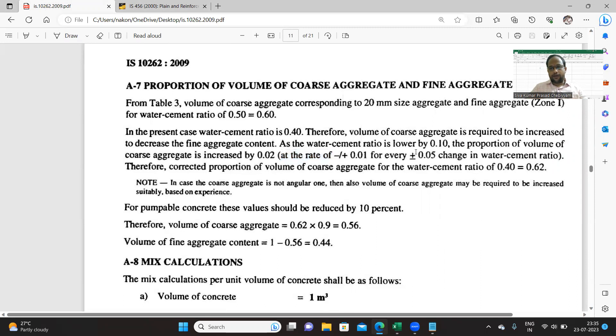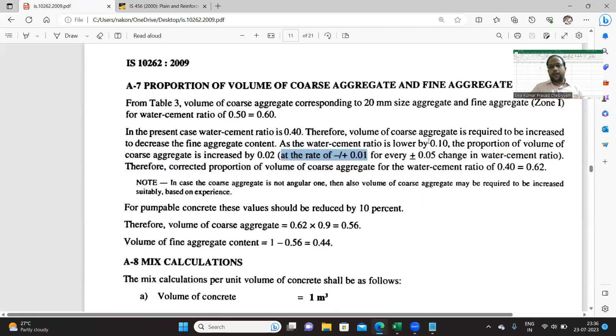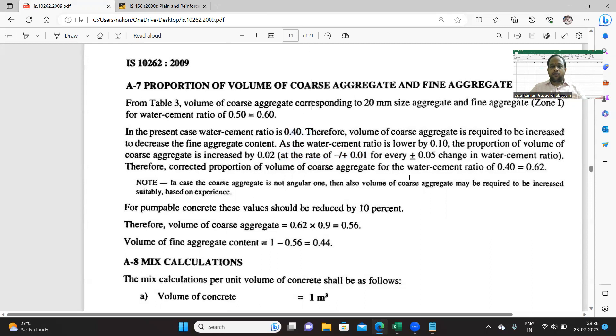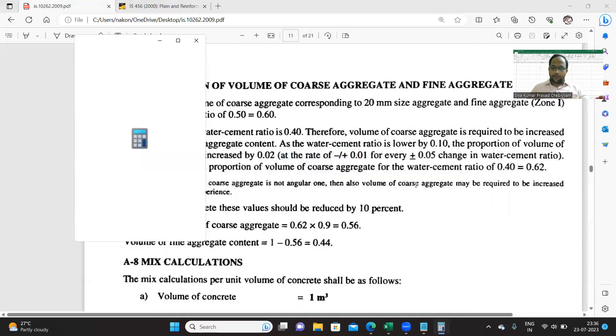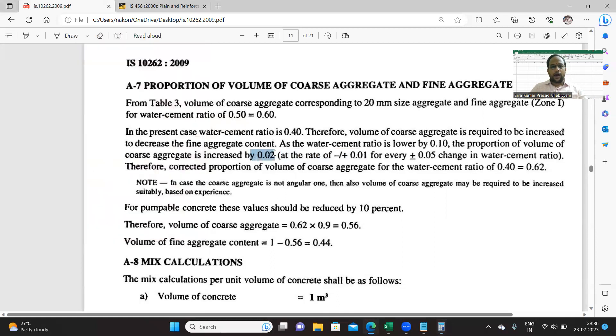If your water-cement ratio is plus or minus 0.05 change, then you should make a correction of plus or minus 0.01. So in our case, the water-cement ratio calculated was 0.4, so the difference is 0.5 minus 0.4, and this value divided by a change of 0.05, that is 2 times 0.01, which is 0.02, so you should add 0.02.